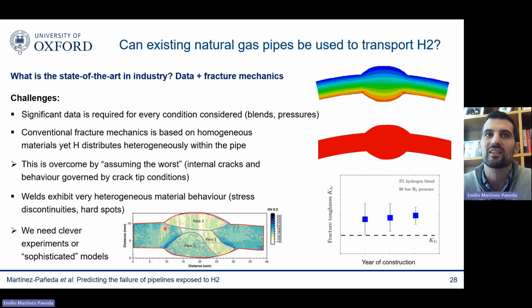So that's a problem. This approach is fine if you have a homogeneous material, but you don't have a homogeneous material here. And so this is a challenge. It's also a challenge not only because you don't have a homogeneous material, but also because, as you see, you have basically a composite. You have jumps between heterogeneous materials. That's going to create raises in the stresses. That's going to create hard spots. So that's going to be quite challenging. Not only do you need to understand these materials individually, but you need to understand how they behave together.